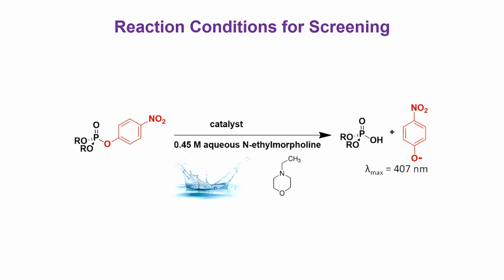You have to think about, when you hydrolyze toxic chemicals, what are the byproducts you are making? Because they could be just as toxic as the chemical you started with. If you hydrolyze a fluorine and get F-, and if you have water molecules around, very quickly you could form HF. If you know anything about HF, if you inhale it, that will kill you just as fast. So you can't just say, I want to hydrolyze a toxic chemical. You also want to understand the reaction, what you are making, and how you can capture that. And that's where the base comes in, it will capture the F- very quickly, before it becomes HF. And we need to replace that beaker of water.